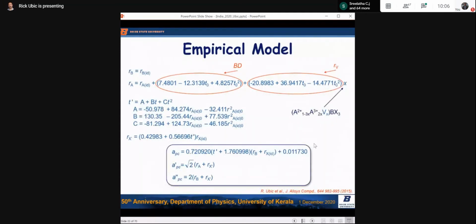So I'm going to summarize the first part of that model here. B is the Shannon B. RA has 3 components: Shannon, bond deformation, vacancy size. T prime is a function of T, and these are its lattice coefficients, A, B, and C. And once you know T prime, you can stuff that into this equation for the anion size. And once you know that, you're off to the races. You have 3 ways you can define lattice constant then: using T prime, using A prime or A double prime, which uses the AX prime or BX prime. All right? So that's a nice, handy summary of the first part of our model for A-site vacancies.